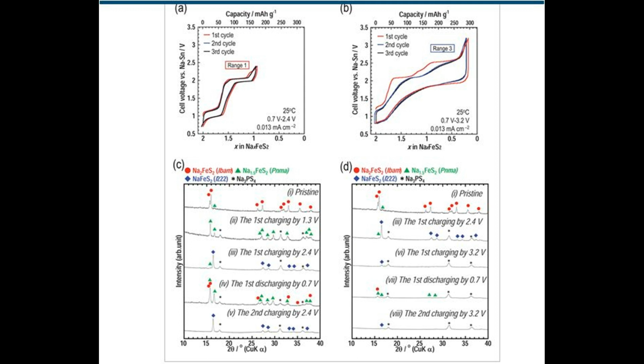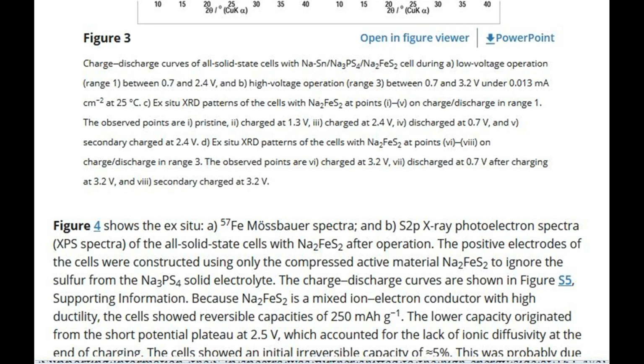Charge-discharge curves of all solid-state cells with Na-Sn/Na3PS4/Na2FeS2 cell during a, low-voltage operation, range 1, between 0.7 and 2.4 V, and b, high-voltage operation, range 3, between 0.7 and 3.2 V under 0.013 mA cm-2 at 25 degrees C. c, Ex situ XRD patterns of the cells with Na2FeS2 at points 1 to 5 on charge/discharge in range 1. The observed points are 1, pristine, 2, charged at 1.3 V, 3, charged at 2.4 V, 4, discharged at 0.7 V, and 5, secondary charged at 2.4 V.